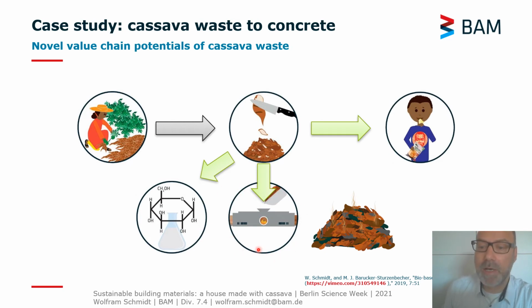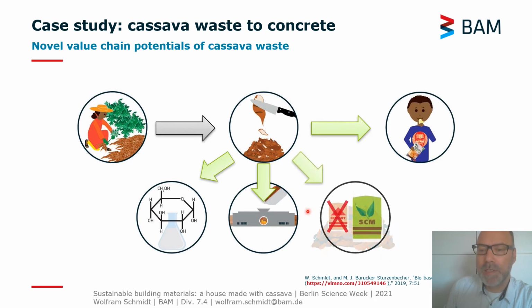There's still a high organic component if you do it the right way. In the first step, you can go for a pyrolysis, or you can do it without carbon emissions and obtain additional precursor components. And after that, you can still burn it and derive ashes which have cementitious properties. So these ashes can be used to replace Portland cement clinker, which is much higher in carbon footprint, and this way additionally contribute to better climate.